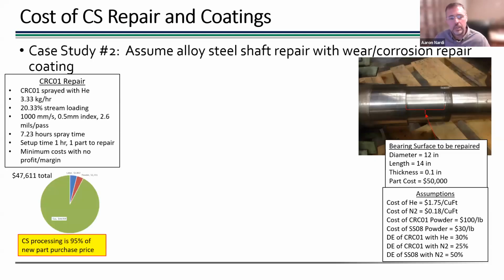And now, if you start to look at a helium repair with this material, this is CrCo1. It's a chrome carbide nickel material. It's used very commonly to repair steel parts like this. Even with a pretty high stream loading, not incredibly high, but pretty high, it's still going to take 7 hours to put that material down. So your cost of doing this job with helium would almost be as much as the whole part cost. So you really can't do that.